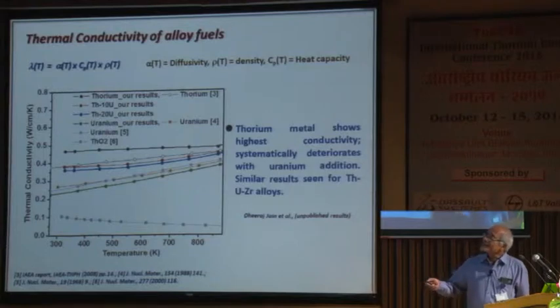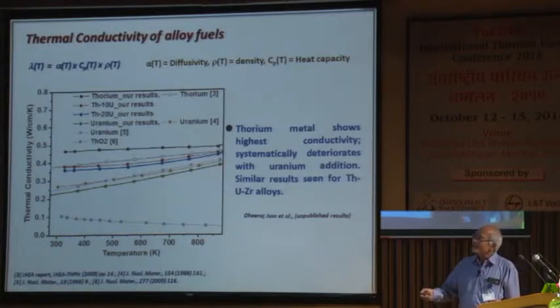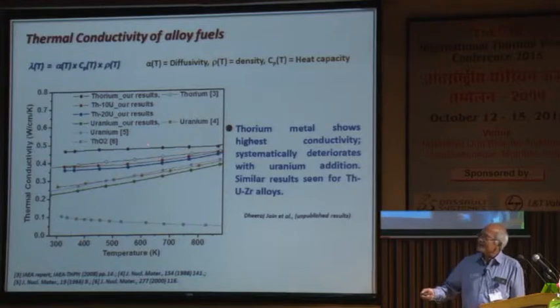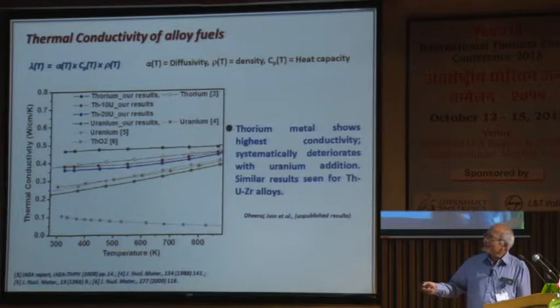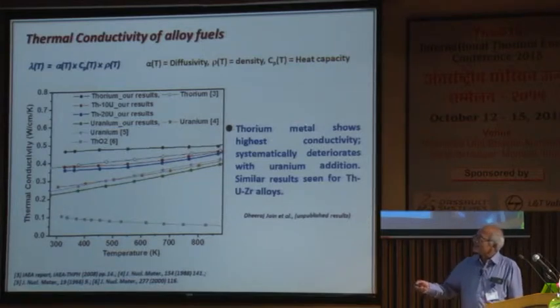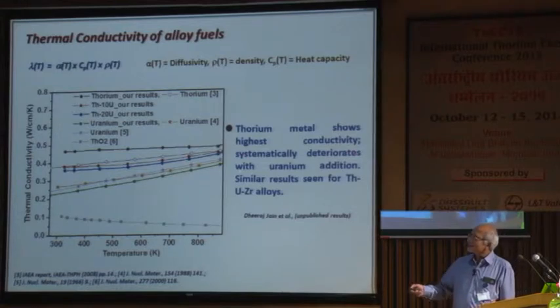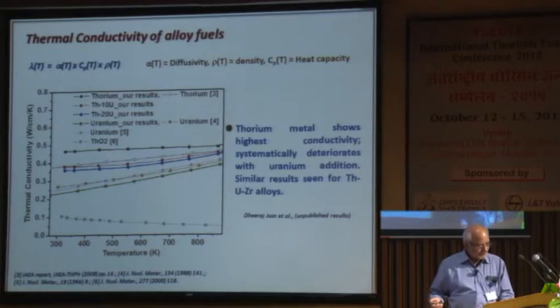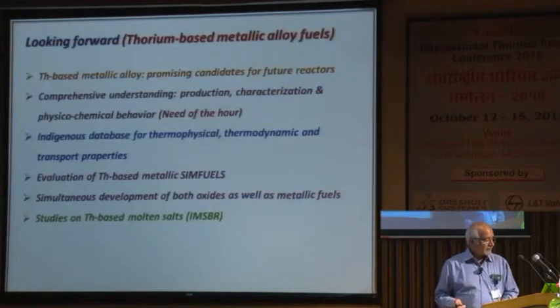The thermal conductivity of alloy fuels has been measured, and this is the consolidated picture here. This is thorium, this is uranium, and thorium-10 uranium and thorium-20 uranium lie somewhere here. The take-home message is that thorium metal shows higher conductivity, which systematically deteriorates with uranium addition, and similar results are also obtained for thorium, uranium, and zirconium alloys.